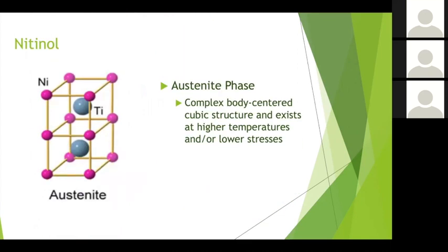Austenite is a complex body-centered cubic type of structure, and it's a very rigid structure. You'll notice that the nickel is all around the titanium, and it's a real rigid phase. This phase of the metal occurs with high temperatures or low stress. So in order to get nitinol to convert to an austenite phase, you have to cook it at a high temperature. Or if you take a file out of the box when you first get it, say a ProTaper file, and you put it on the countertop, that's under low stress. So that file is in an austenite phase, okay?